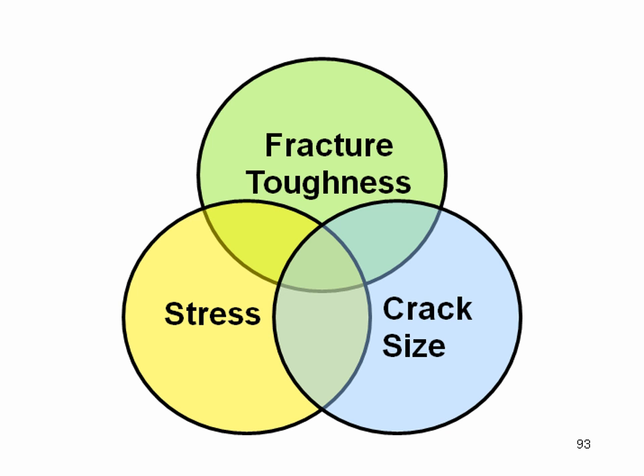Fracture mechanics primarily relates three variables: the fracture toughness of the material, the applied or residual stresses, and the presence of a crack, the orientation of the crack, and the size of the crack in the member. So we have three primary variables that we deal with to avoid fracture. Now, we want to optimize the toughness, and we want to minimize the stress and minimize the crack size in order to preclude fracture. So let's start by looking at fracture toughness, the things that happen negatively if we leave them alone with the jumbo sections, and what AISC has imposed to help to mitigate those kinds of concerns.